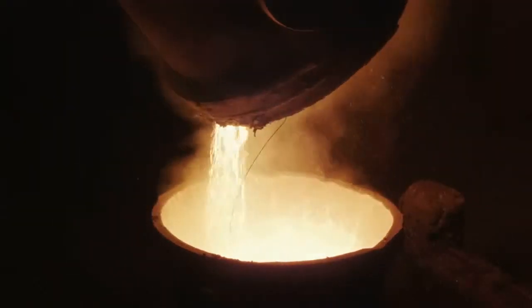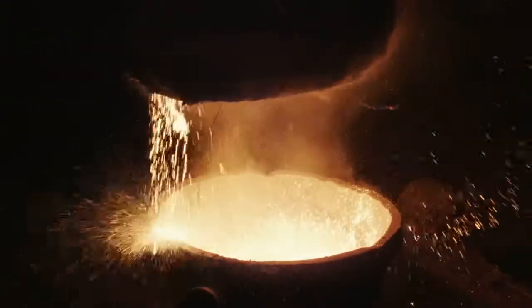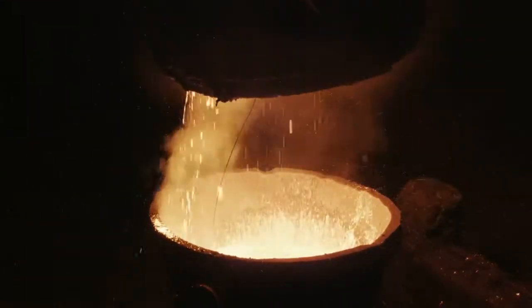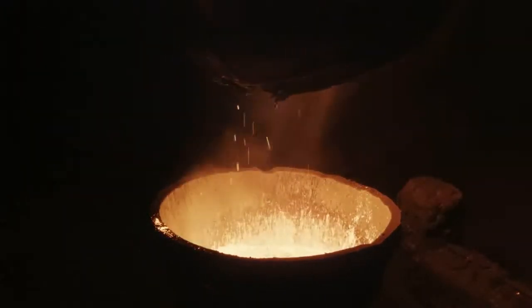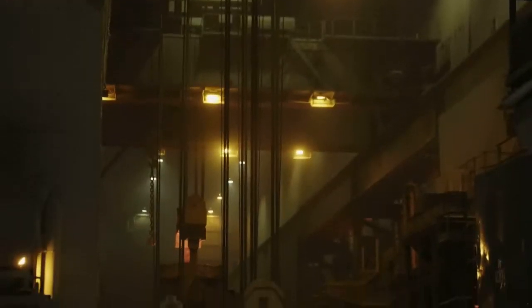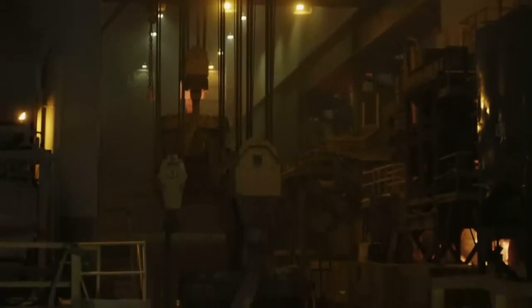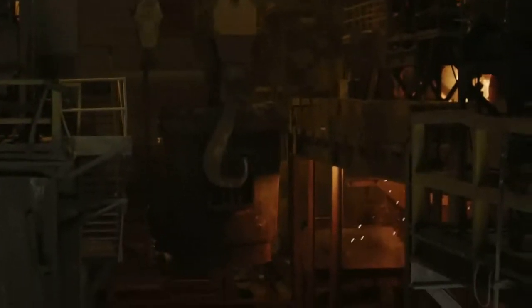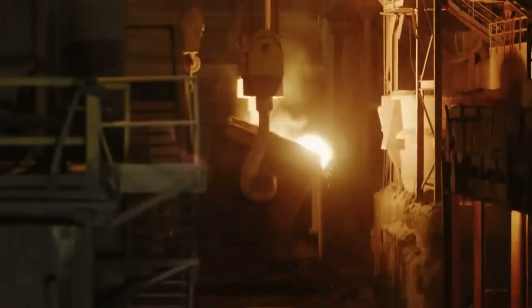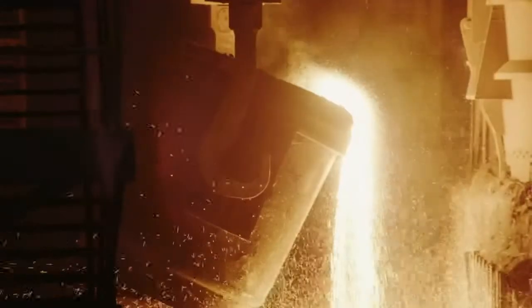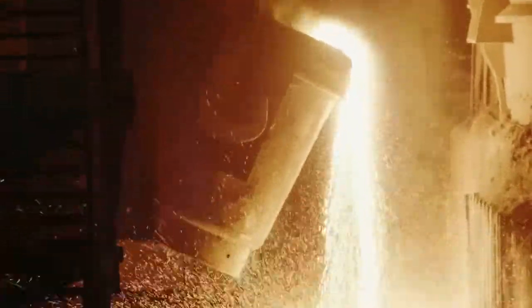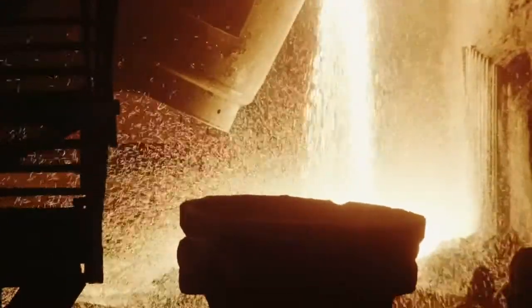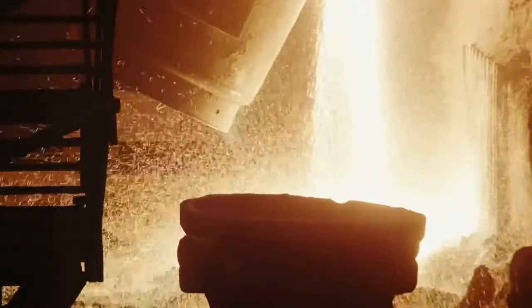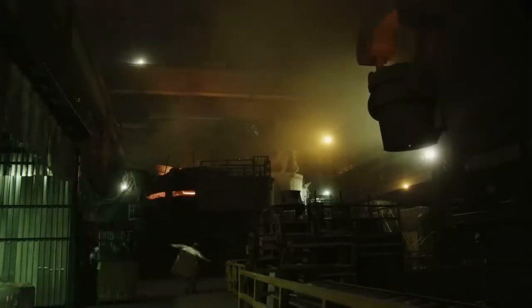Many mills use electric arc furnaces, or EAFs, which require much less in the way of natural resources versus traditional blast furnaces. For every ton of steel produced by SDI, we eliminate the need for 2,500 pounds of iron ore, 1,400 pounds of coal, and 120 pounds of limestone, and we use significantly less energy in the process. The EAF process also produces 67% less carbon equivalent emissions. In addition, 95% of our scrap comes from within 250 miles of our plants.